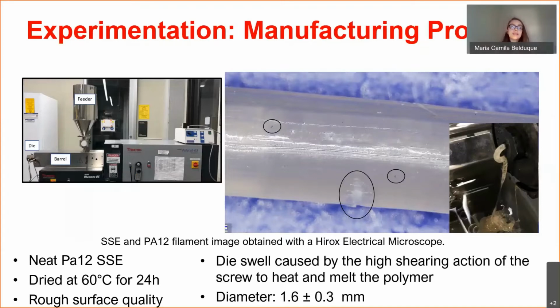This elastic effect is known as die swell, and is caused by the high shearing action of the single screw to heat and melt the polymer. Consequently, it was not possible to add the strontium ferrite in this machine. And we can see in the image the processed PA12. It also has some contamination and a rough surface, and the diameter is about 1.6 millimeters.